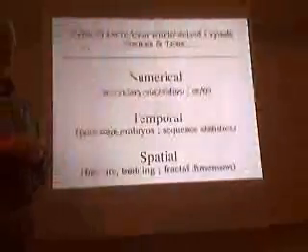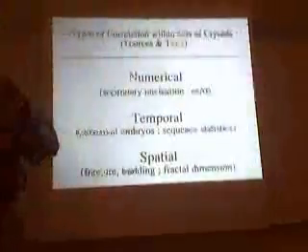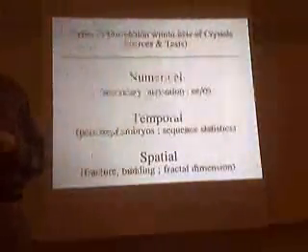And finally, there's spatial correlation. If you do not stir, it's still possible that tiny pieces break off and float away. In that case, if you have fracture or budding from the crystals, then you can get spatial correlation. One hand tends to be in one region and another hand in another region. Sometimes that could be very obvious, but sometimes it's not, and you have to have some way of measuring it to see whether it's random or not. We used fractal dimension to analyze that situation.